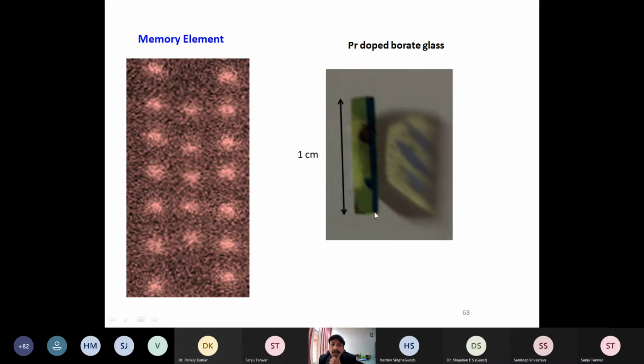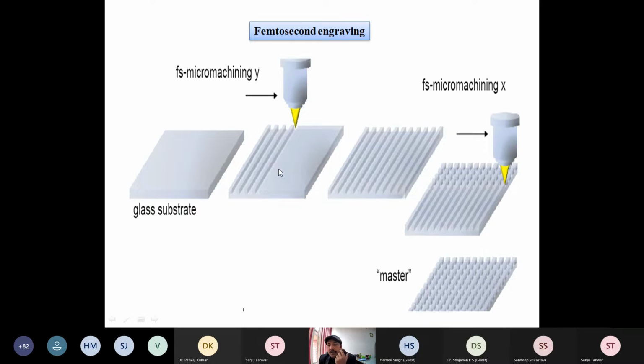So this blue strip you can see here, within that we make these white spots that you are seeing. That white spot gives you a red color when exposed with blue light. And if you expose this with UV light, this white spot is going to be erased. Also you can make a master mold with the help of a femtosecond laser by a simple engraving method.